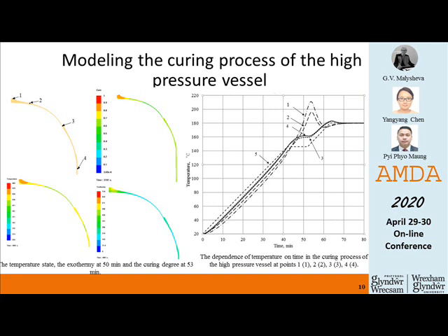It was found that during curing, uneven heating takes place not only along the bottom contour, but also in thickness. The highest temperatures were recorded at point 1, with an increase in the duration of heating. Not only does the temperature increase, but the area of unevenly heated surface also increases. Similarly, the degree of curing changes. It was found that the greater the thickness, the greater the amount of heat released during the curing process. This additional heat flow leads to an increase in the temperature and the degree of curing.